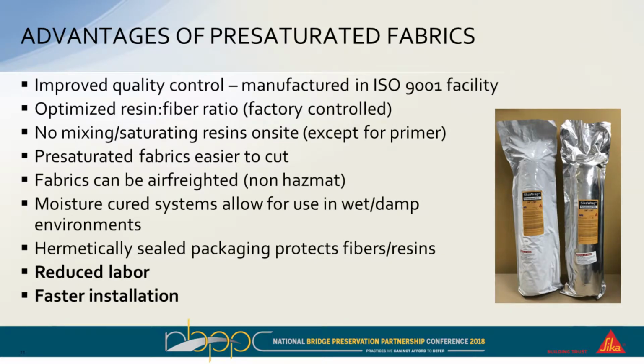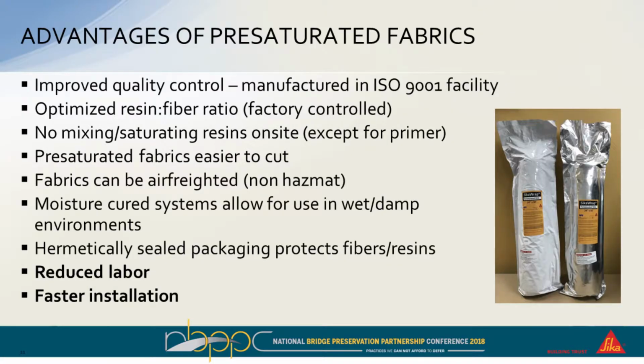So if we look at the use of pre-saturated fabrics for civil engineering or bridge applications, now what we can put together is an improved quality control, something that's manufactured in an ISO 9001 facility under controlled conditions, with an optimized resin to fiber ratio. So again, we're not relying on the contractor to mix up so much resin and apply so much fabric. It's all done in a controlled condition under optimized conditions. The fact that you can do this without having to make the contractor mix up the epoxies and actually do the saturation on site not only makes it a better quality system, but it also improves the productivity. They can do it a lot faster. The pre-saturated fabrics are much easier to cut because they get less fraying since they have the resin already built into them. They can also be air freighted.